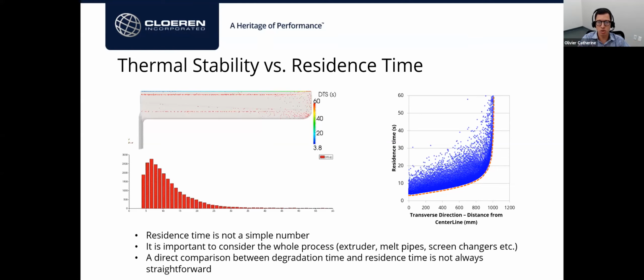So residence time in the extruder, in the melt pipes, in the screen changers, melt pumps, and so on and so forth. Whatever is in between where the pellet is dropped into the extruder to the die lips, all this is a complex system with a complex residence time distribution. So while it's nice to have information on how fast the material degrades from rheology, it's also hard sometimes to directly apply it to the system, or at least we have to keep in mind that the system is complex and it's just not a 5-minute residence time.